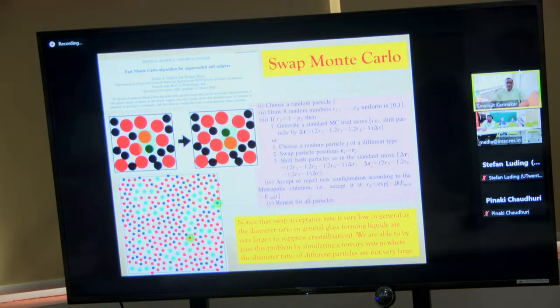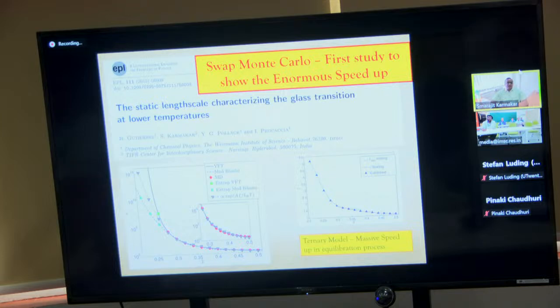And so I came back to Hyderabad, and some years went by before I actually took it up, and I discussed this with Itamar, who was my first postdoctoral mentor, and we did this work together. So we actually introduced a ternary model, a ternary glass former, and the model particle size ratios are such that this swap acceptance rate went up by at least a factor of 100.